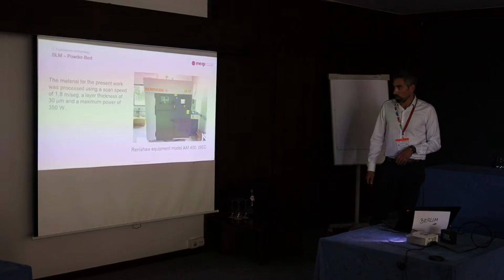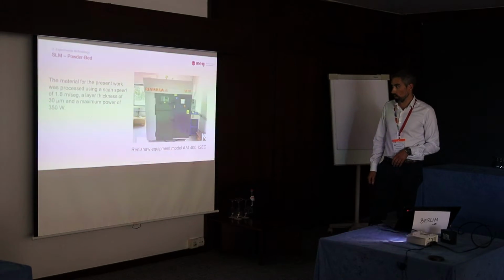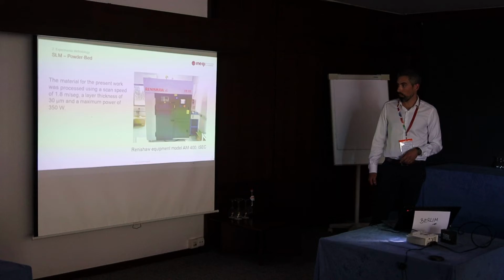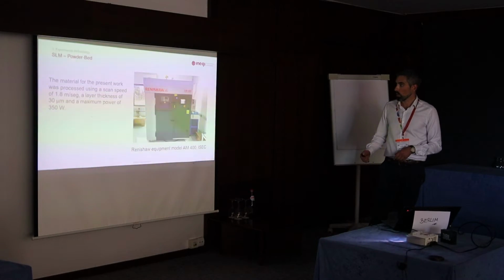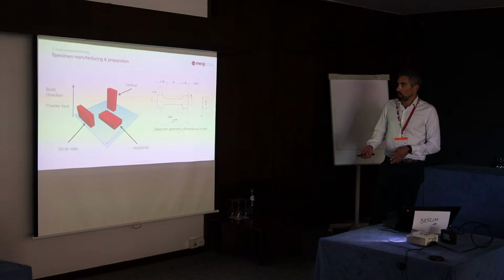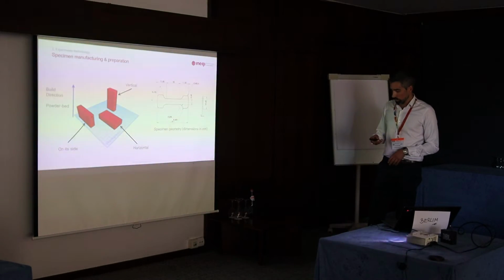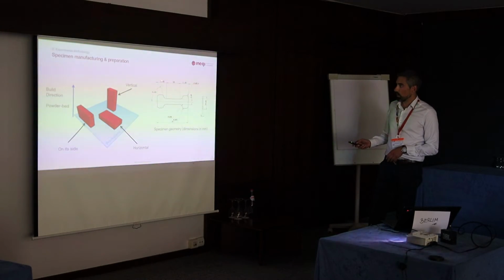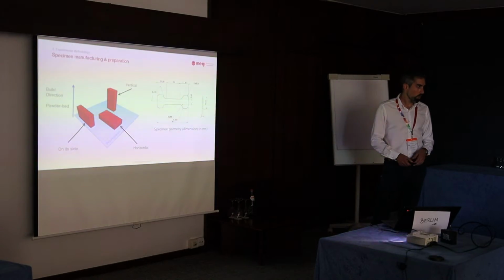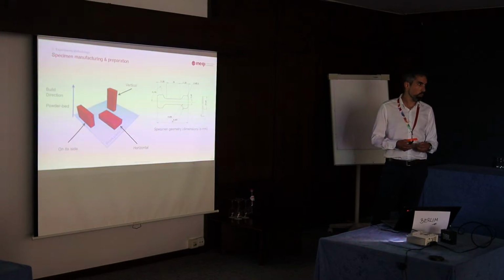This was the equipment that was used to produce the components from which the specimens were manufactured. Basically, just an overview of the setting, and this would be the specimen with a millimeter of thickness, let's say a micro-flat tensile specimen, so that we would be able to test it in the split Hopkinson bar.